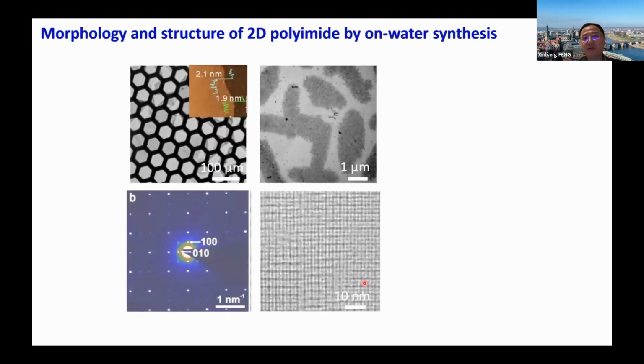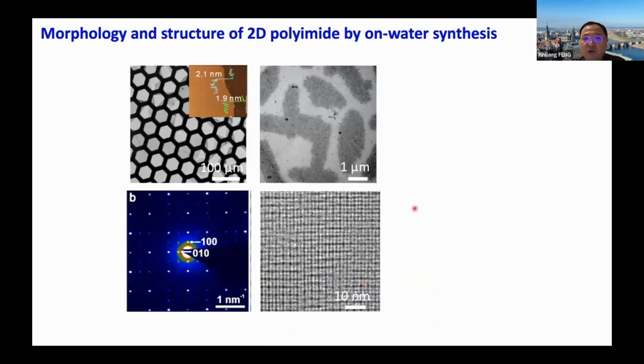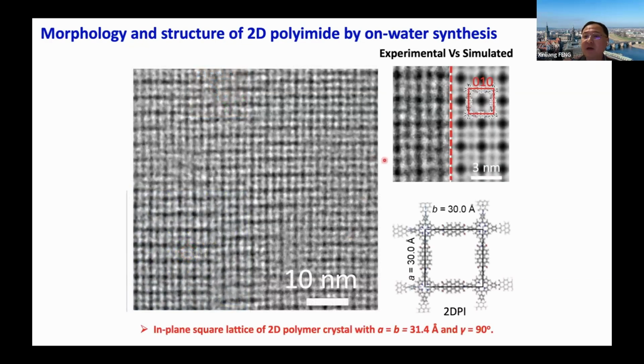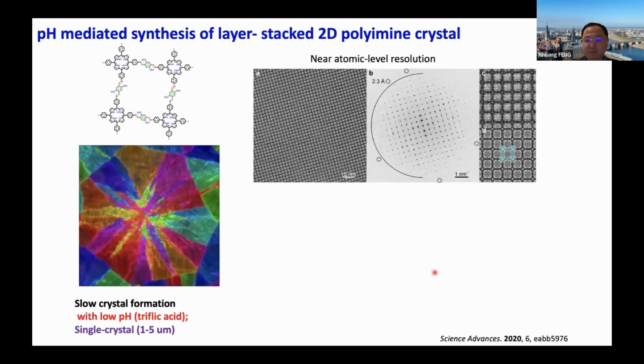And firstly, we need to prove the structures. And this will show you the morphology, with the single crystals, a few micrometers in size, okay? And with the high-resolution TEM and the electron diffraction, which the last speaker just showed, beautiful scattering and the X-ray or the microscopy, you can resolve the structures with molecular level resolution. And from that, you can confirm that is a single crystal, with a very thin few-layer material. We have a unit size about 3 nanometers, which is very precise.